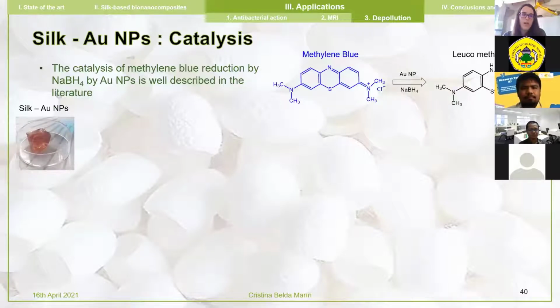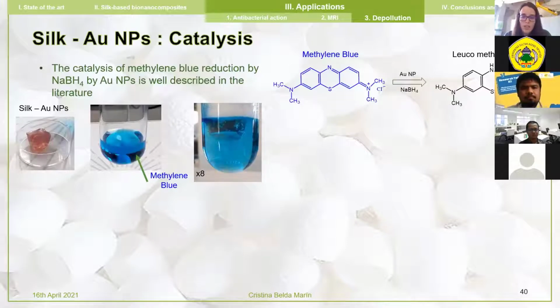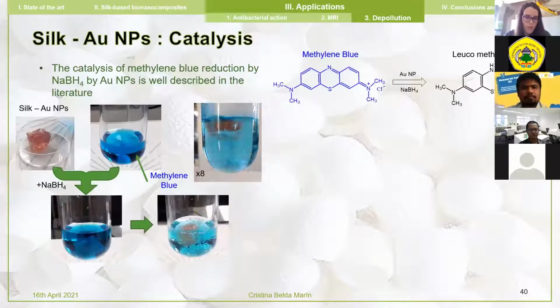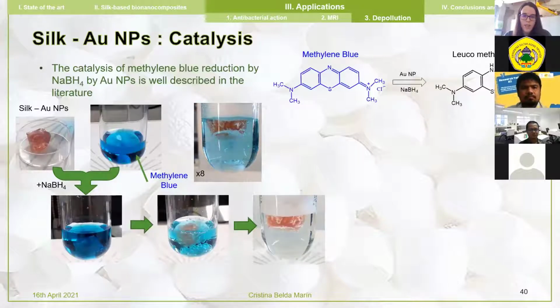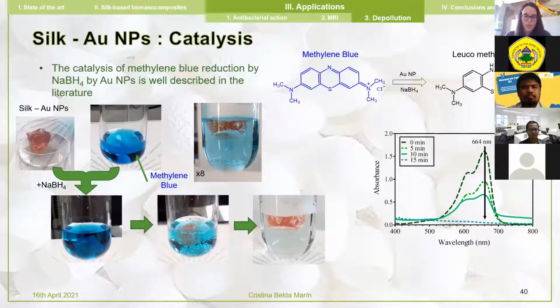So here we have our silk hydrogel containing gold nanoparticles, and you can see from the video that with time, our colorant is catalyzed. And at the end, we have no more methylene blue, neither within the silk hydrogel, nor within the solution. And very important, of course, this is not the case when we use only silk hydrogel without gold nanoparticles. So we have characterized this through the light absorption of methylene blue, and maximum absorption is found at 664 nanometers. As you can see, within only 15 minutes, we arrive at zero absorption. So the entire methylene blue has been reduced.